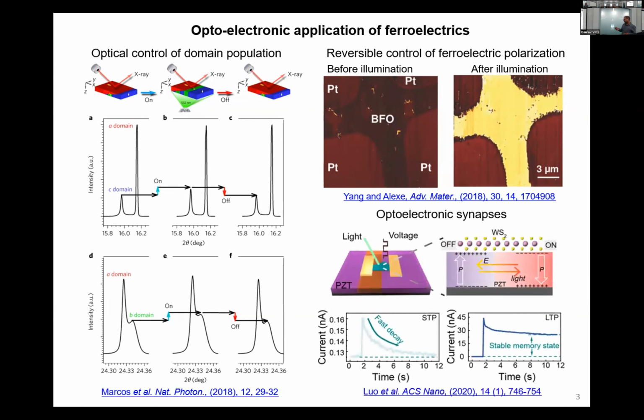For example, in this particular case, they developed this device, optoelectronic synapses, which is good for neuromorphic computing. So they used two different materials. One is PZT, which is not so sensitive to light, and then this tungsten sulfide layer on top of it, which is sensitive to light. And altogether, this device worked well, and it was shown that it can act as an optoelectronic synapses.